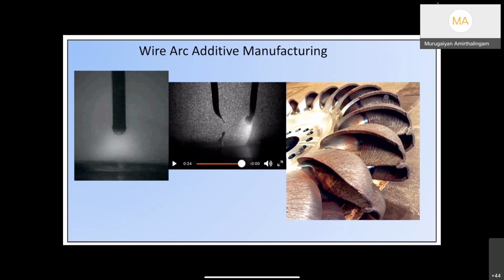So to print this, we can also use what is known as a functional gradation. If we start with a single steel wire, and slowly, gradually change the composition of the molten pool in such a way that when we come over here, this can be a highly corrosion resistant material, say for example titanium, or we can also use a nickel-based superalloy when we start depositing the impeller parts. So this kind of functional gradation is also possible with very high productivity, where the localization can be made to meet the various demands that are encountered during in-service.